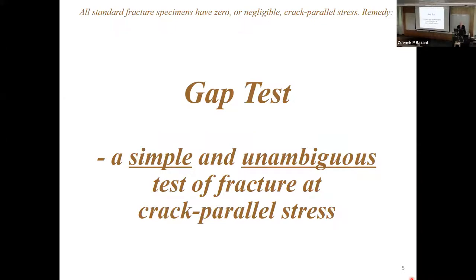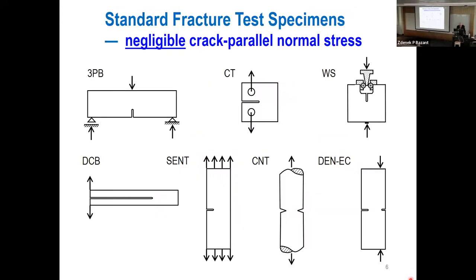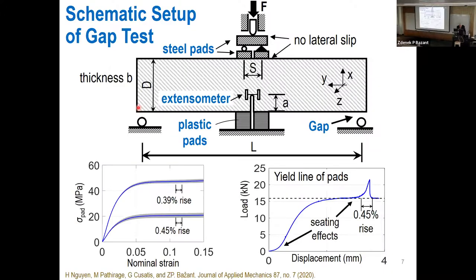First, one new result, the gap test, which we found 1.5 years ago, which sheds considerable light on the problems in the fitting of data and is an important check. It is simple and unambiguous. The point is that the standard fracture specimens all have negligible stresses parallel to the crack plane, effectively zero. The gap test solves this in a very simple way. We take a standard notched specimen and install it at the ends with a gap. That gap closes after loading, when the pads, here plastic pads, compress enough. They exhibit plasticity, so we keep the load constant, and that produces crack-parallel stress throughout the process.